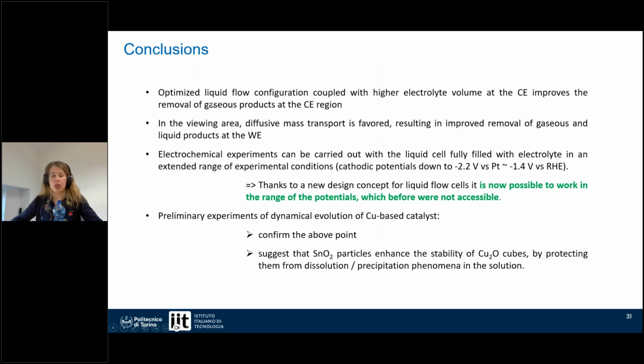So with this, I come to the conclusion. I hope I have convinced you that the modified and optimized flow configuration is very interesting. It helps the electrolyte to be flown more efficiently through the cell. And in this configuration, in which we have higher electrolyte volume at the counter electrode, this improves the removal of gaseous products from the counter electrode region. And in the viewing area, the diffusive mass transport is favored, resulting in improved removal of gaseous and liquid products from the working electrode, so from the catalyst at the working electrode.